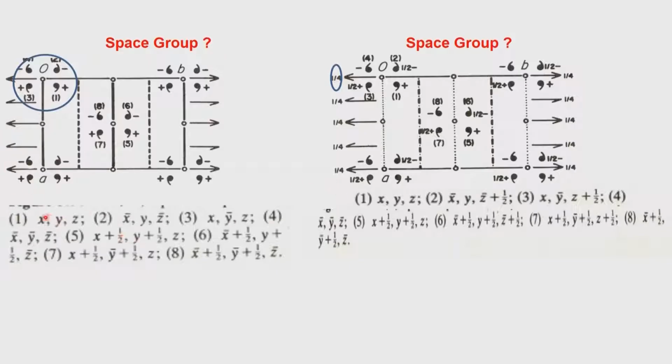So the diagram here and the set of equivalent points, we can now verify with respect to the occurrence of 2/m. Since it is 2/m symmetry, there are no translations that are required, and therefore the mirror, the two-fold and the center of symmetry intersect at 0, 0, 0, and the C-centering generates the one at half along x, half along y. What is very interesting in this particular space group is that because of the presence of the center of symmetry as well as the C-centering, we develop two additional symmetry elements. One is the 2-1 screw axis, which is at 1/4 at this point, and the other is the glide plane, which is moved by 1/4.